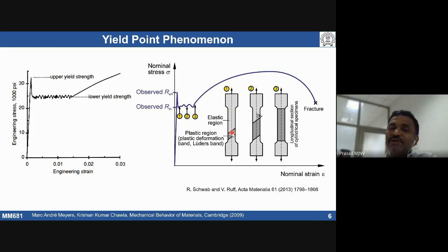Do not get confused: these bands have nothing to do with slip lines and slip bands. These are different from slip lines and slip bands. They are simply called Lüders bands. These bands form at a stress concentration region initially, and then they propagate from one position to another along the entire gauge length of the specimen. Multiple bands can be generated depending on stress concentration regions. If the stress concentration is maximum at only one position, we may see only one band. If the stress concentration happens here and there, then bands will form from both sides.